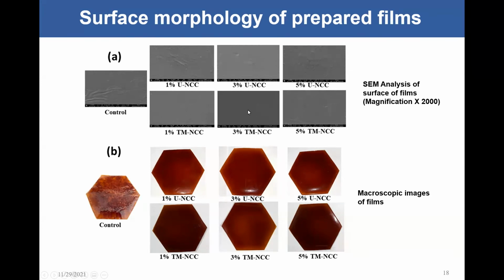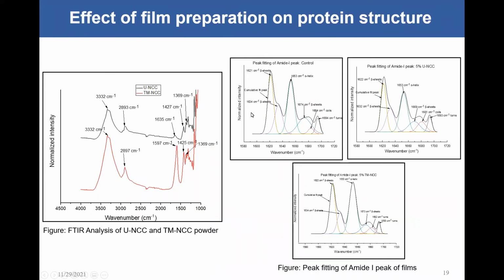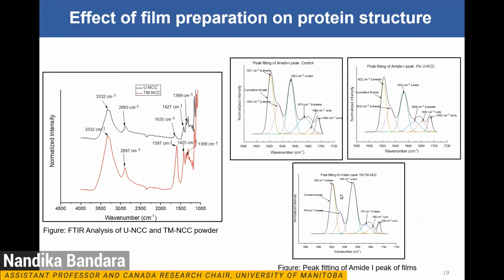At 3%, you can see that there's a smooth surface on the material. The other thing is we look at the protein structural changes as well. With the TEMPO modified nanomaterial addition, we did observe protein structural changes at the secondary structure level, where we see a reduction in the beta sheets and an increase in the unordered structure. This is something that we observed in our previous research on canola protein-based adhesives as well, where there is an increase in the unordered structure due to nanomaterial-induced protein denaturation.